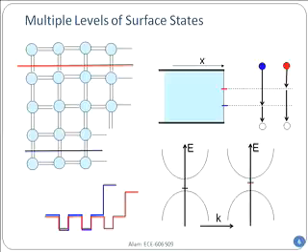That's why surface states are so dangerous. You know, copper or gold gives you one level, sits in the middle, it helps a certain recombination, no problem. On the surface, there is a series of them throughout the whole thing. And therefore, lots of ways for the electrons to come down to the valence band and recombine. Recombination we don't want for the time being. There are devices where we want it, but for these, we do not want it. And therefore, an entire series of levels, it will be full. Remember, each state is coming from the consequence of this thickness modulation or height modulation.